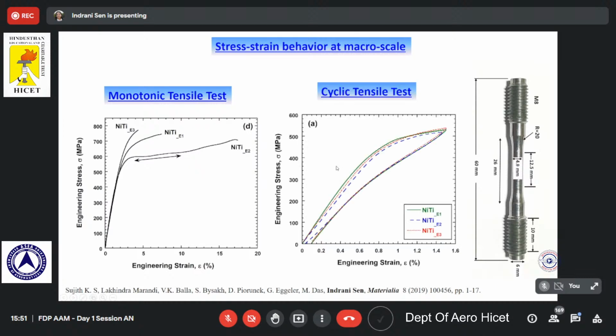To check for the recoverability, we did the cyclic tensile test also. This blue one here shows significant amount of recoverability. To confirm that further, we have done the digital image correlation, where we are doing the cyclic indentation test. You can see that this goes to the red highest strain, and then we are unloading it, so it comes back to the green and bluish tinge here. And once again, we are going to increase the strain, to check that it is coming back to almost the initial position. Almost more than 90% of recoverability is what we have figured out.